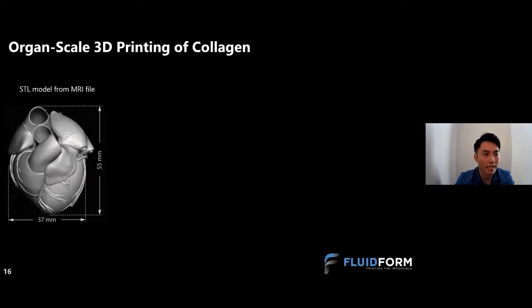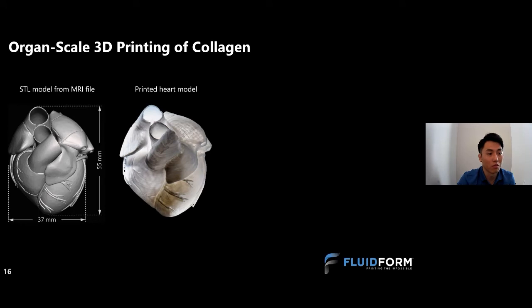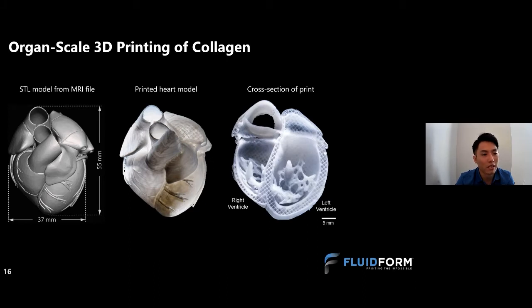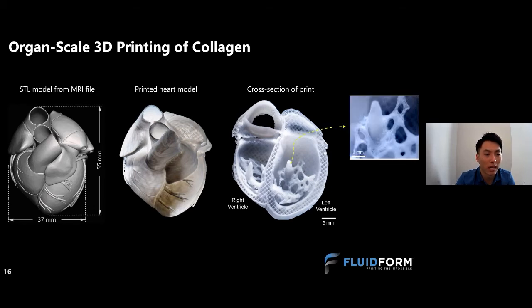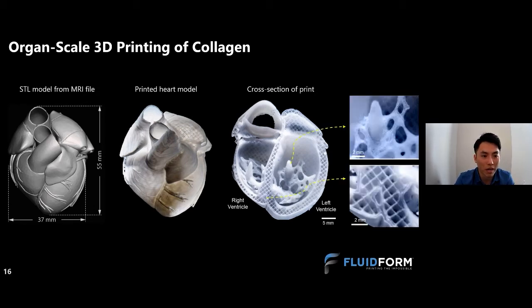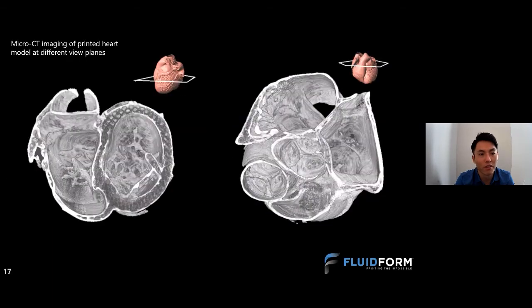So we took an STL model derived from a human MRI file, turned it directly into a print. So shown here is a printed heart model, roughly the size of a large strawberry, printed entirely out of collagen type 1. And you can see that it really recreates a lot of the fine details of the file itself. When we take a cross section of the print, we start to see that we recreate some of the trabecular structure and also some of the infilling structure.